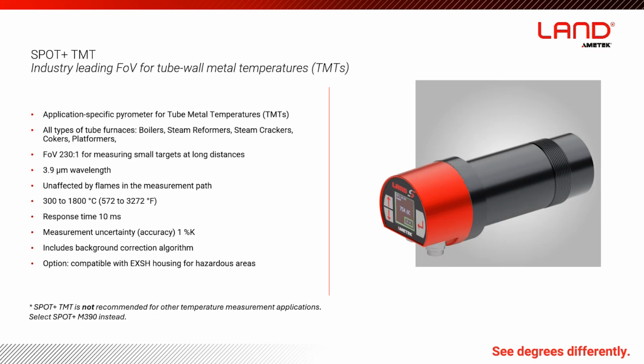Unlike the two more general purpose pyrometers that we've been talking about, this one has a 230-to-1 field of view. So it has a very narrow field of view, so you can look at small objects at a considerable distance and still get an accurate measurement. Like the 390, it works at 3.9 micron wavelength, so it successfully sees through flames, smoke, typical furnace atmospheres.